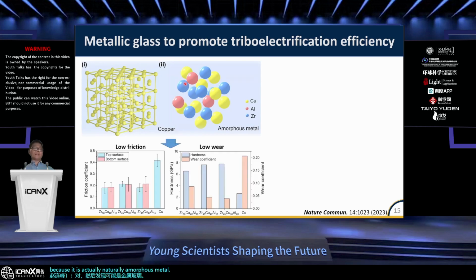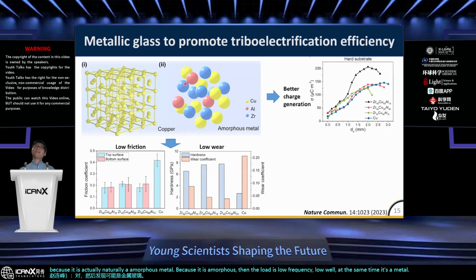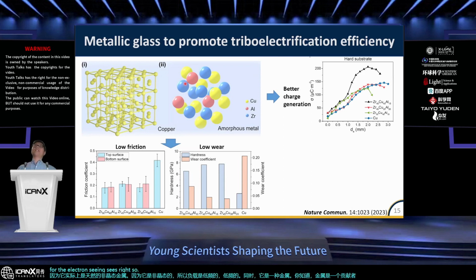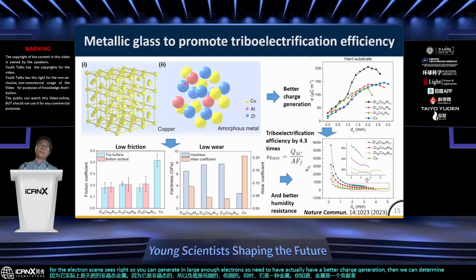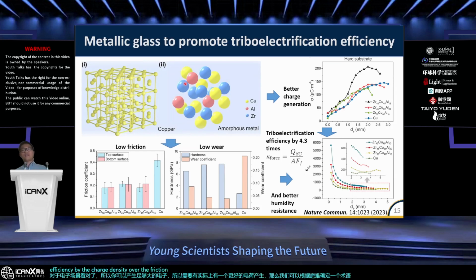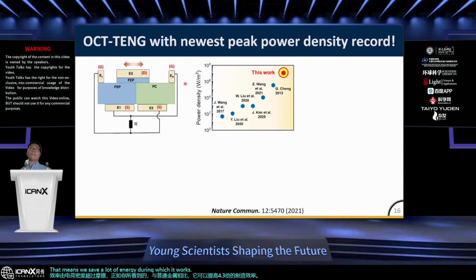Because it is amorphous, the friction is low, and the wear is low. At the same time, it's a metal, and the metal is a contributor of electron sources, right? So it can generate large enough electrons, and it can actually have better charge generation. Then we can define a term called the triboelectrification efficiency, the charge density over the friction. As you can see, compared to the regular metal, it can be enhanced by 4.3 times in triboelectrification efficiency. That means we save a lot of energy which was wasted through the wearing.